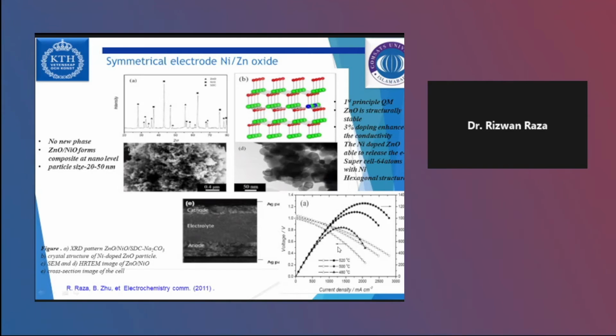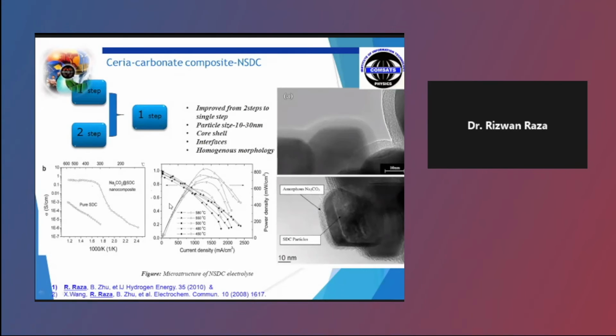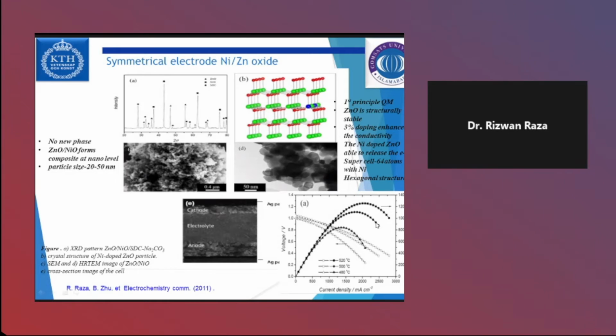And if you can see, in the previous one the power density was around 800 milliwatt, but here, after introducing these compatible electrodes, the power density is increased from 800 to 1200, so more than 1 watt, 1 watt per centimeter square.